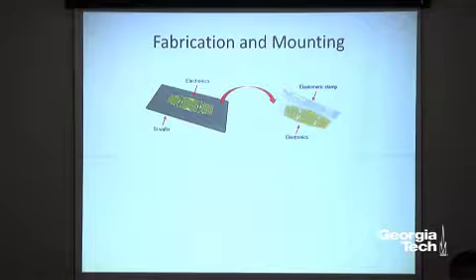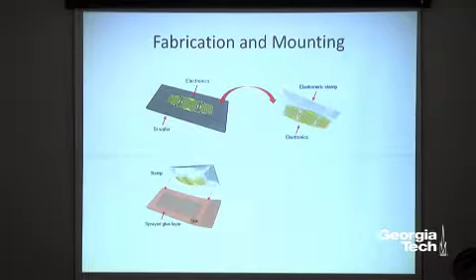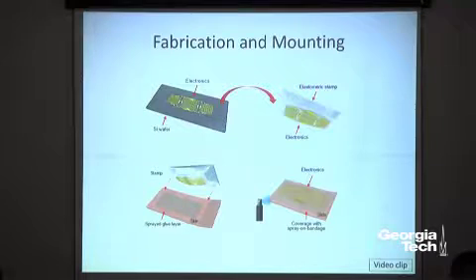Now you can put this onto your skin or onto a flexible membrane, stretchable membrane, medical bandage, anything like that. But here, as an example, we can put this gold electrode onto the skin directly by using a sprayed glue layer. And then after transferring, you can encapsulate with a waterproof polymer thin coating about 1 to 2 micrometers. Then you can wear this electrode for more than 2 weeks, up to a month or more, depending on how you encapsulate it. Right?